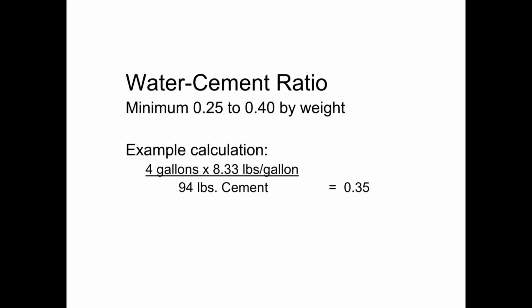It would be unusual to see a mix in a precast plant that has a required water cement ratio greater than 0.45. Anymore, it's fairly uncommon to see one with a water cement ratio greater than 0.40. So generally, we're going to be looking at water cement ratios between 0.25 and 0.40. Now, on that 0.25 end of the spectrum, keep in mind that that is the minimum amount of water needed to react with the cement.